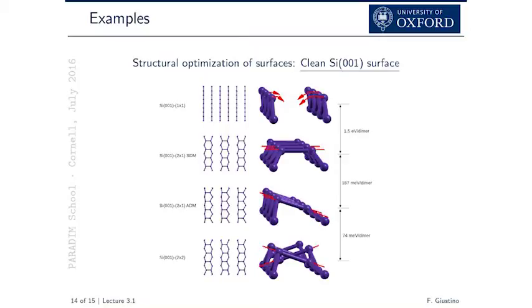So the reason for that, at this point, is the fact that there are 2 electrons at the same energy. If you perturb the system, the degeneracy will be broken. So we have a state at low energy that can be filled by 2 electrons. So what will happen is basically that these will be filled by 2 electrons, and here we have silicon in sp3 configuration. So here there will be a state with 2 electrons left. This is a bit more stable than this one and much more stable than this one.